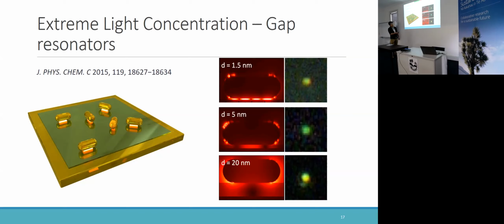But when the gap spacing is 20 nanometers, we can see the field, on the same scale, is much weaker than the 1.5 nanometer case. This means the smaller the gap spacing, the stronger the field is concentrated at the gap. From the scattering image of single particles, at the gap spacing of 20 nanometers the scattering image is very bright. But at 1.5 nanometers it's very weak, which means the incident light is absorbed in this case, so the scattering image is darker.